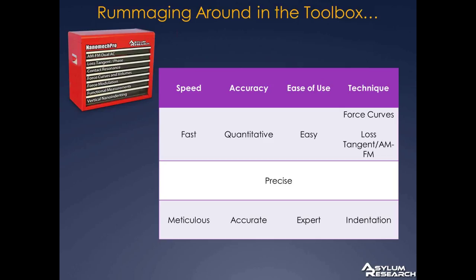The two techniques I'm going to focus on today, loss tangent and AM-FM, are fast, easy, and provide quantitative images of the sample stiffness and the loss tangent, basically the ratio of the dissipated to the stored energy, on a wide variety of samples. Because they're based on tapping or AC mode, they're fast, easy, and quite adaptable. You can do it on samples with hundreds of nanometers of roughness down to samples with single atomic defects. We recommend verifying any of these measurements. If you really need to have an accurate number, we recommend verifying these with other kinds of tools. For example, indentation, force modulation, contact resonance, just to name a few.